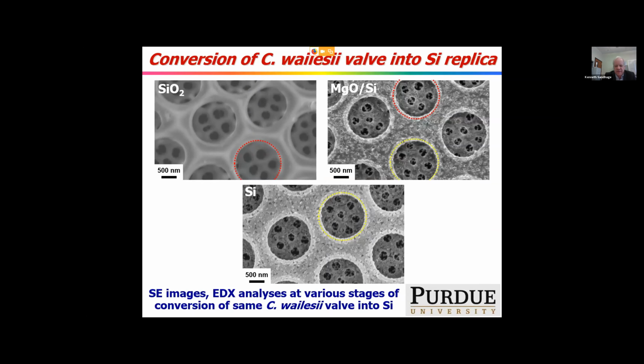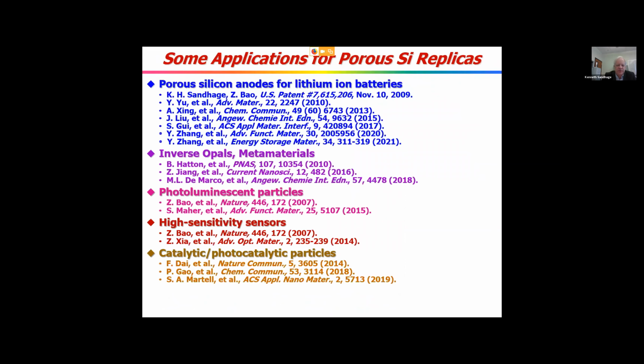Even if you look at the yellow circles, even the fine structure beneath the fine pores in the big pore are preserved. So we can get preservation down to the order of several tens of nanometers resolution with this process. So you might ask, well, what's it good for? Well, porous silicon has a number of applications, not the least of which is as anodes potentially for lithium-ion batteries.